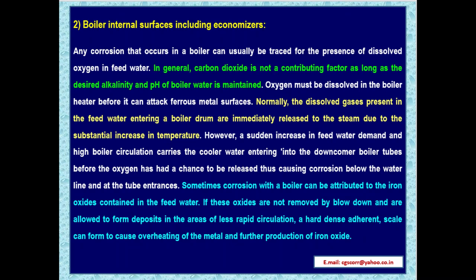Normally, the dissolved gases in the feed water entering a boiler drum are immediately released to the steam due to the substantial increase in temperature. However, a sudden increase in the feed water demand and high boiler circulation carries the cooler water entering into the downcomer boiler tubes before the oxygen has had a chance to be released, thus causing corrosion below the water line and at the tube entrances.